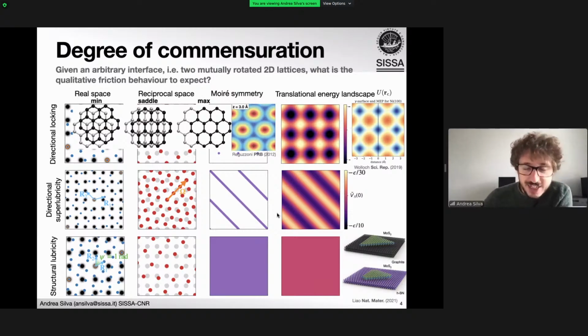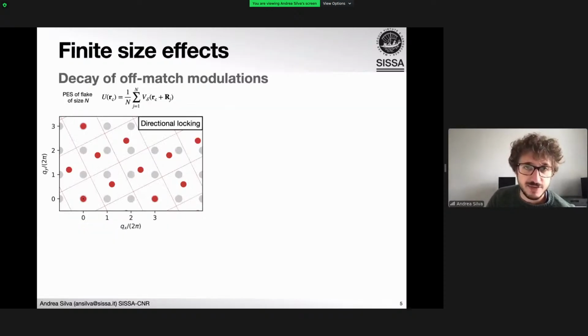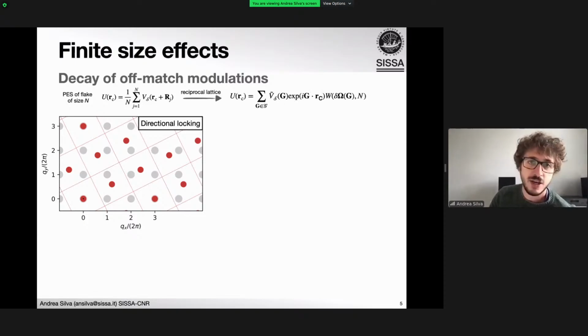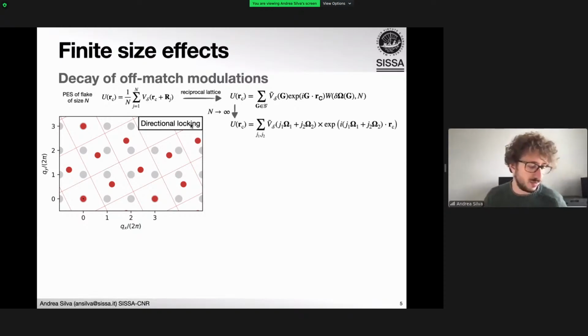As I said, the scaling law is kind of what defines structural lubricity, going from finite size, increasing the size, and the sublinear scaling. And we can describe that with this approach. So if we take a finite flake of size n, we can write the potential energy surface in real space by summing over the particles, or using the reciprocal lattice depicted down here. So we can expand in the Fourier components. And this is for a finite size flake that will go back to the one I showed you before for an infinite system. So here there is a bit of formula, but it can be broken down a bit.